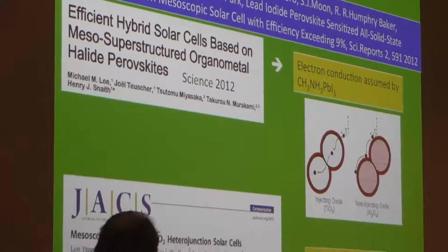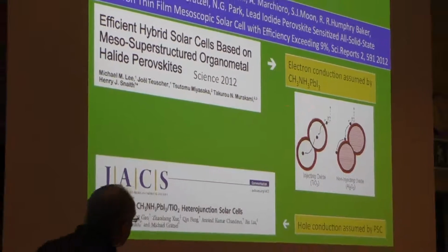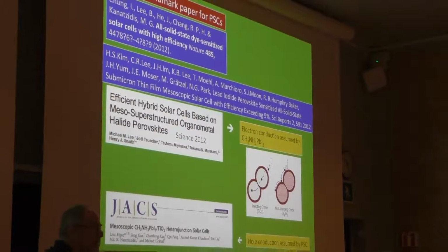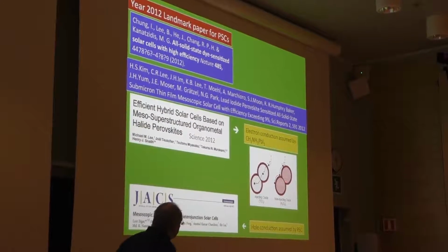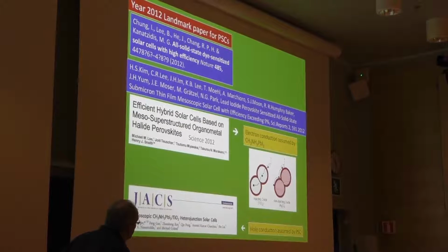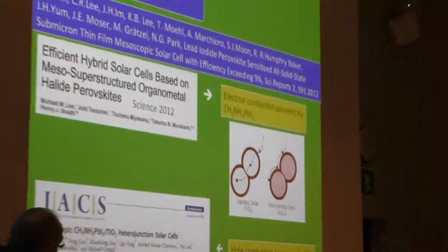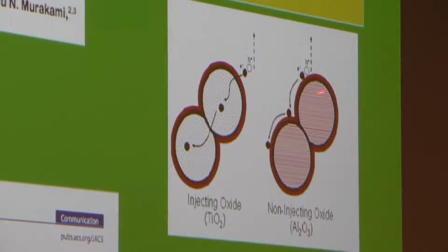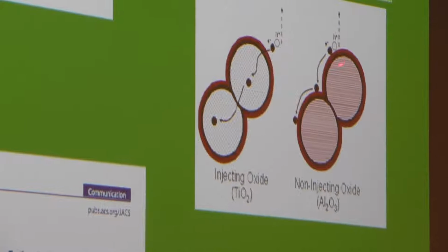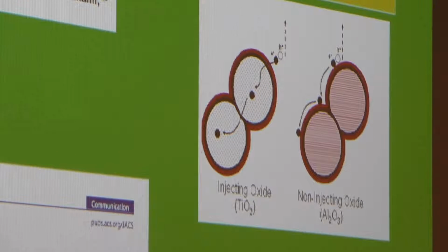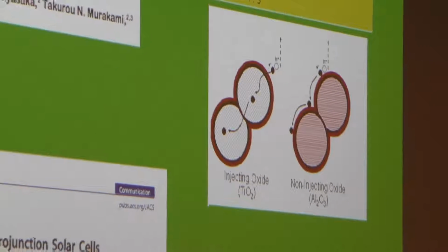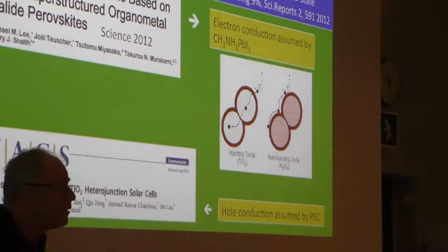There was something in the very early Henry's paper which said that this is maybe something else than just replacing the dye, and that was the experiment they did as a blank first, to check how fast the electron recombines in the perovskite layer. So they used aluminum oxide as an insulating oxide. And very strangely, they saw that the efficiency with aluminum oxide was even higher at the time than with TiO2. So that means that you don't need an injection like in the dye cell from the light absorber into TiO2. The perovskite can really conduct electrons on its own. So that shows that perovskite is another kind of material.